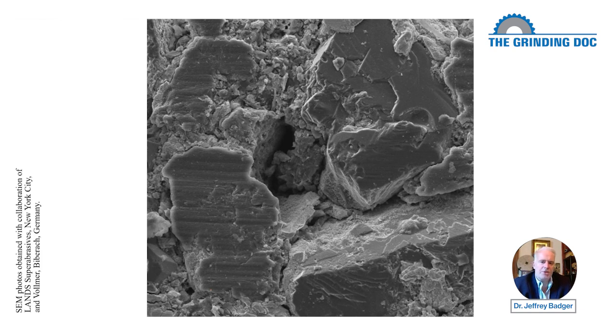So that's the biggest factor causing CERMETs to be difficult to grind: those little hard ceramic particles in the CERMETs are not quite there, but they're getting close to the hardness of the diamond. They dull the diamond, so now we have dull, flat grits in our grinding wheel, and we're grinding with a dull, flat grinding wheel, and the only way to fix that really is to true the wheel.